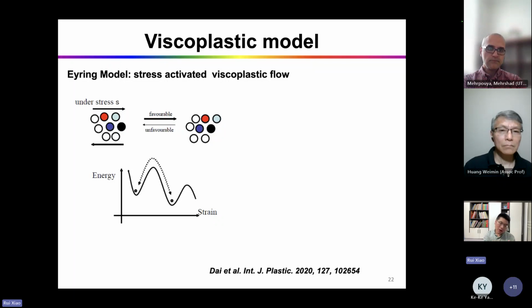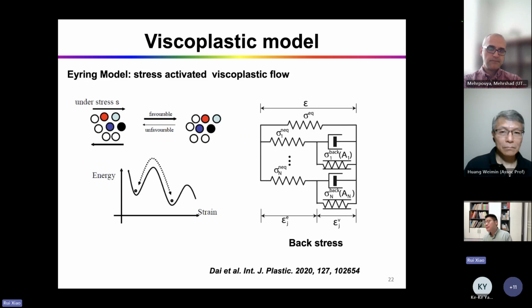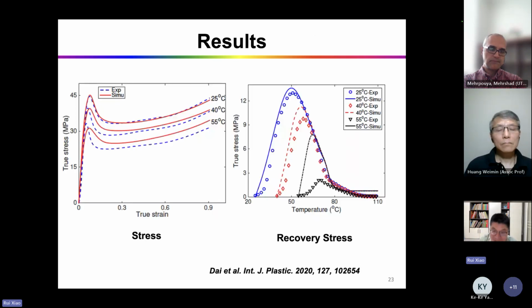That means the polymers have a very large relaxation time, but if you have larger stress, they can drive plastic flow. You also need a hardening mechanism, basically something called back stress. I don't show equations - the equations are complex - but if we have two mechanisms, you can now simulate this beautiful stress strain curve.